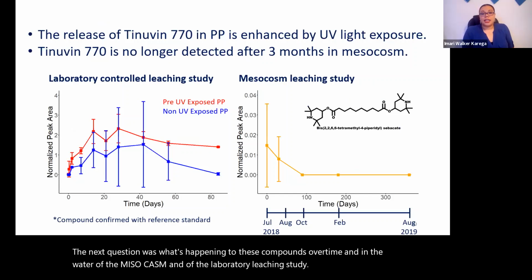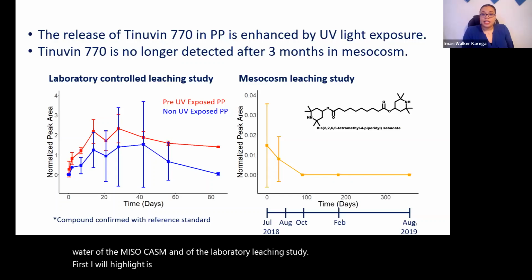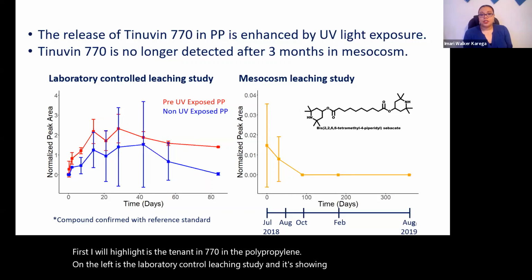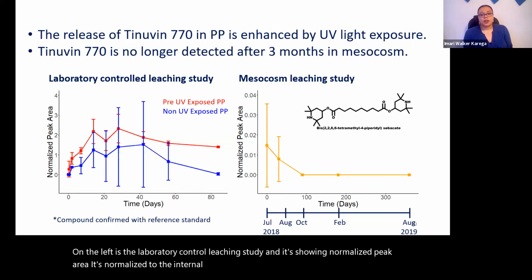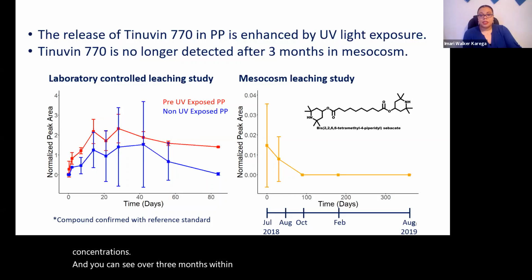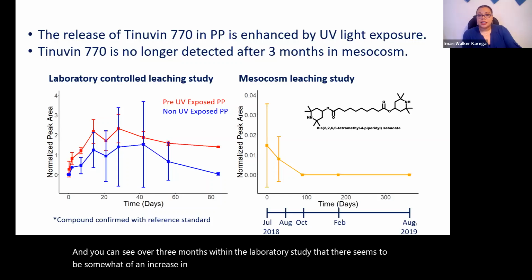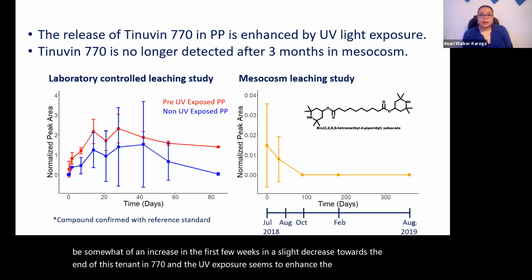First we'll highlight Tinuvin 770 in the polypropylene. On the left is the laboratory controlled leaching study, showing normalized peak area, normalized to the internal standard to understand concentrations. Over 3 months in the laboratory study, there's somewhat of an increase in the first few weeks and a slight decrease toward the end for this compound.